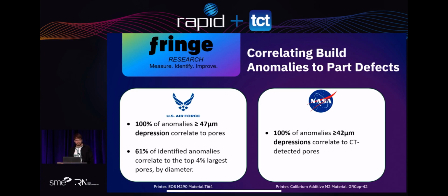Meanwhile, we were working with NASA Marshall Space Flight Center. They're printing with GRCop to serve their liquid engines program. And we found a similar magnitude level that was super strongly correlated to anomalies found in the CT. And what's interesting is these are two different printers, they're two different materials, but the one constant is the layer thickness that's designated by the printer. These were both 30 micron layer prints.